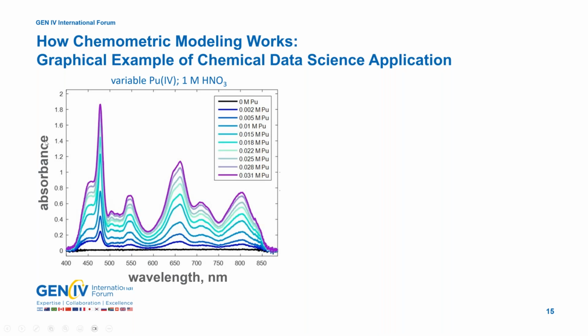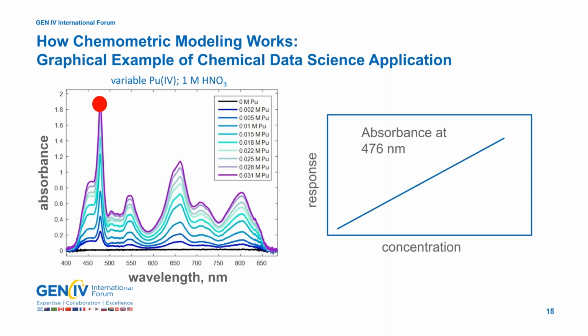In this particular instance, we could actually pick our favorite wavelength and then plot the absorbance of that wavelength as a function of plutonium-4 concentration. Essentially what we've generated here is a single variate calibration curve, or a Beer's law plot. Now forever in the future, if we run into plutonium-4 under these precise conditions, so within 0 to 30 millimolar and in 1 molar nitric acid, we can use this calibration curve to quantify plutonium-4 present in solution.